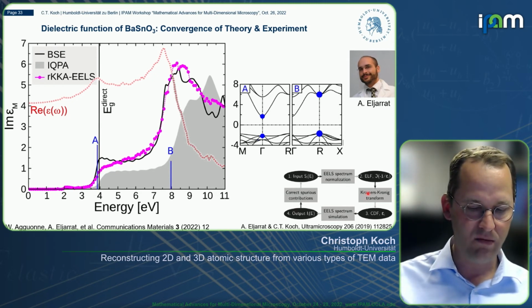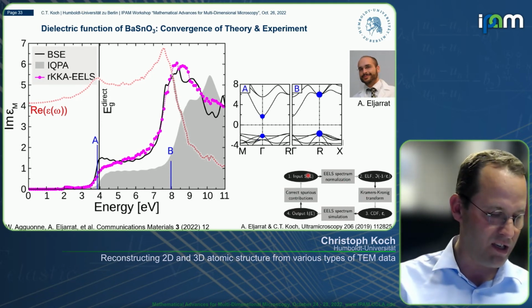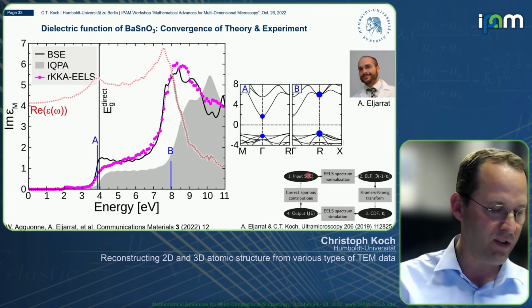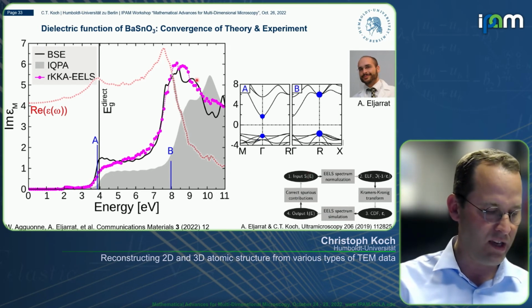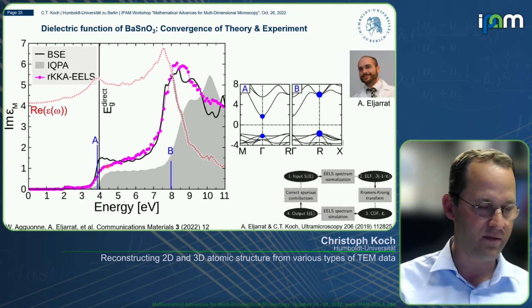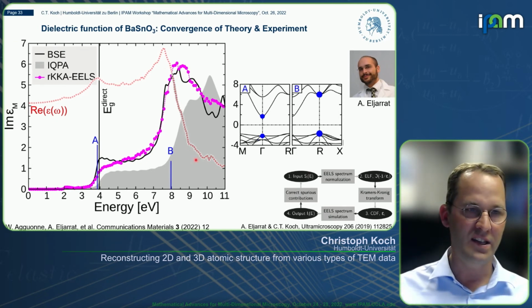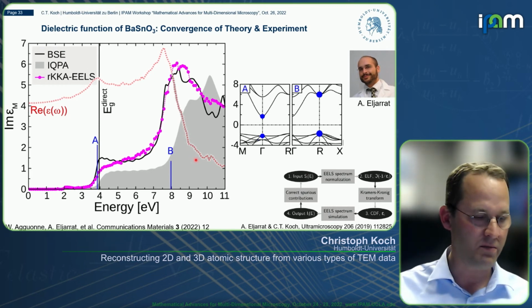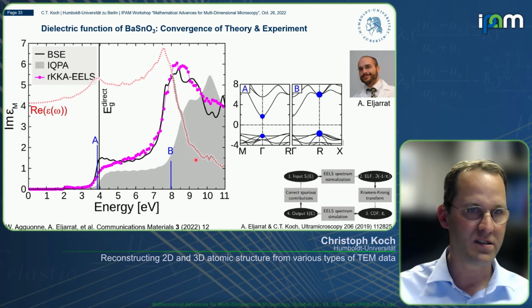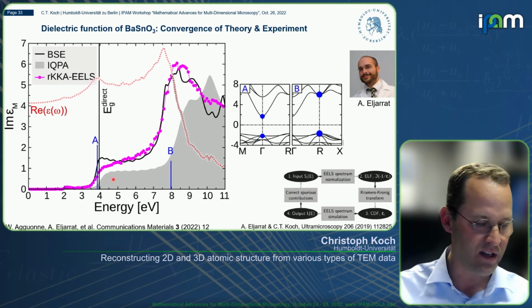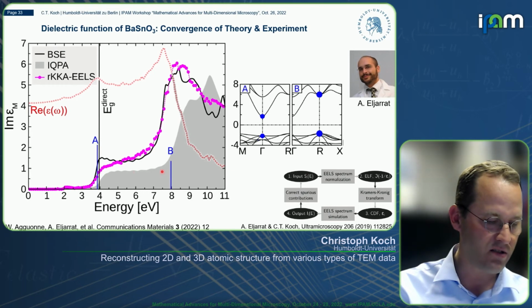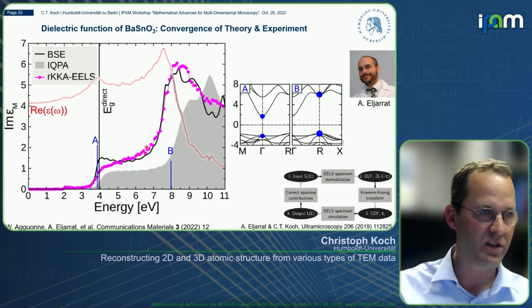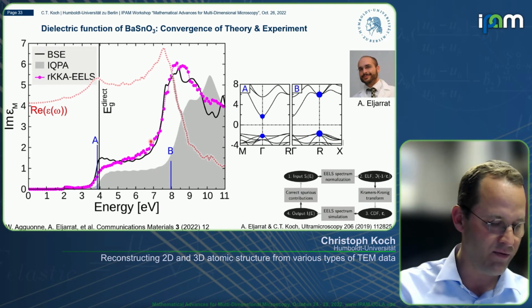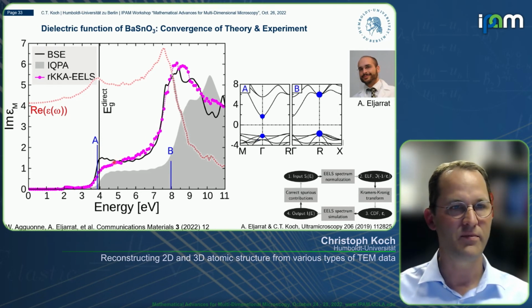So this is really Alberto Eljarrat in my group. He invested a lot into this to make things possible, like you see here, for example, recovering the dielectric function of, in this case, barium stannate, both the imaginary part and also the real part of epsilon of omega. And interestingly, there was a group in our department, by Claudia Draxl, that did different DFT calculations: a standard DFT calculation and also an all-electron calculation using her own code, solving the Bethe-Salpeter equation. And you can really see that if this improved theory is applied, it agrees very well with the experimental data.